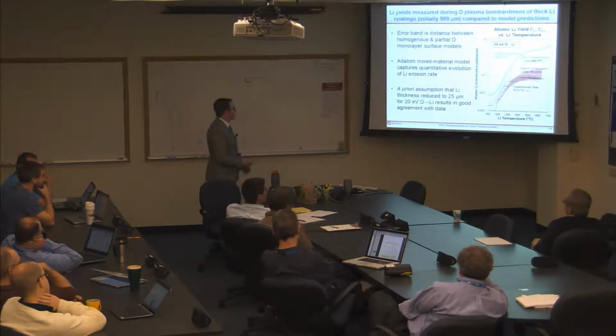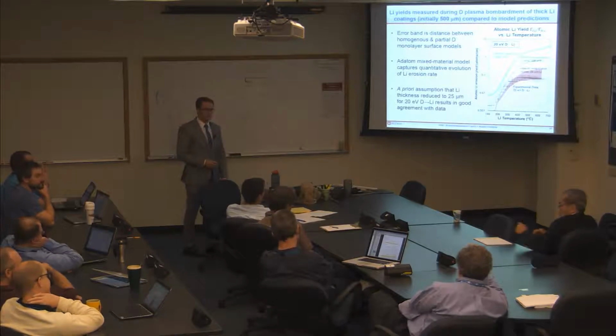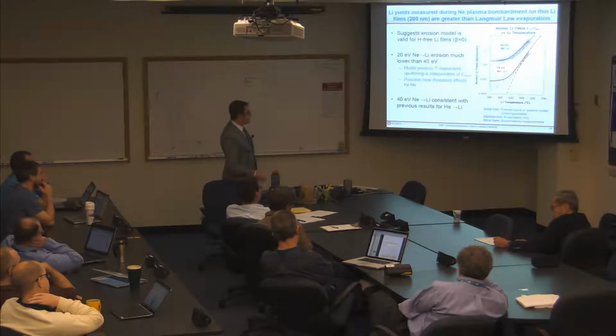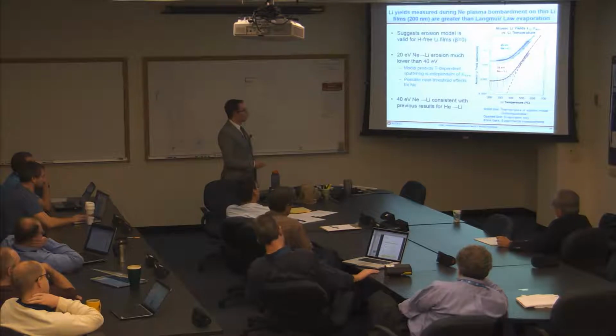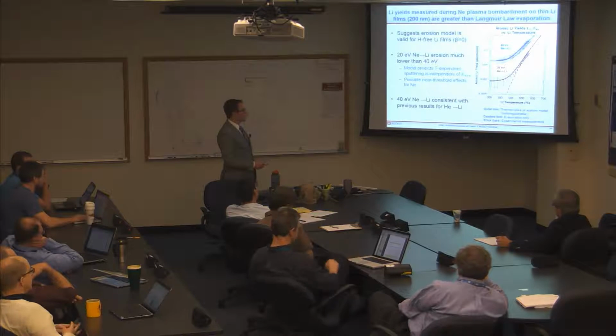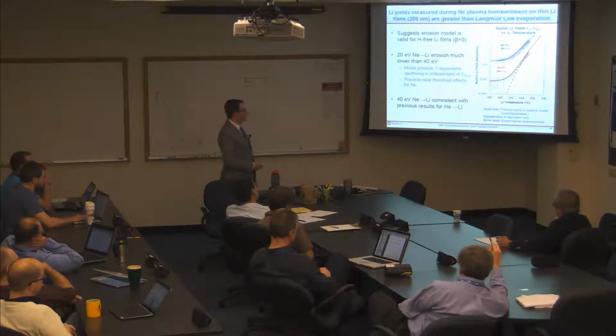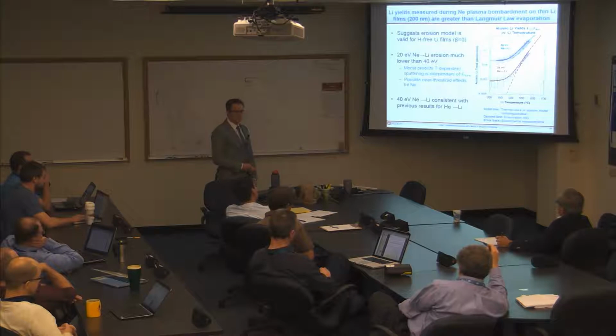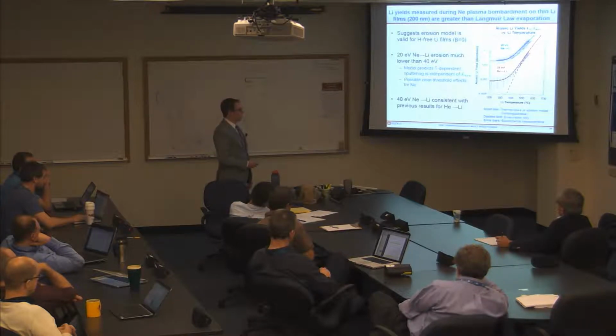Okay, so what about the deuterium? It didn't at 20 eV, but it did at 40 eV. The effects seem to be a lot more pronounced at 40 eV than 20 eV. But that one almost looks like a linear addition. Well, this is a log plot. I'm saying that it's at least converging to the evaporative one. The dotted line is the evaporated rate. So it's converging to that. It almost looks like the difference could be the sum of those two effects with no special add-ons.